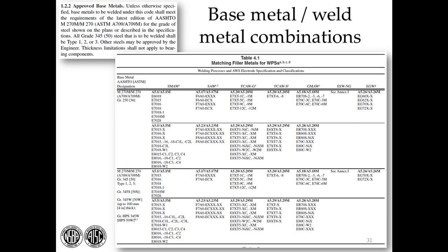If possible, the best thing to do is, during project development, do some chemistry testing of the material that you've got. I mentioned during the presentation that you can check the hardness of your steel and therefore its weldability, basically, using a carbon equivalency formula. D1.5 has a pair of formulas inside, and then there are others that you can find readily through various guidance, and they're very similar. So what you can do is do some chemistry testing, find out what constituents you have, and then use those formulas to discover whether or not your material is too hard.